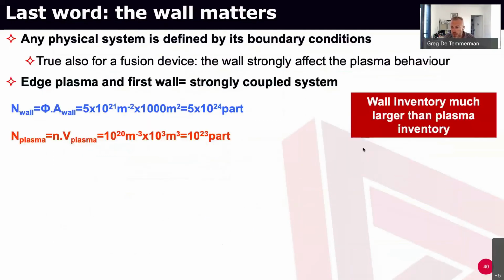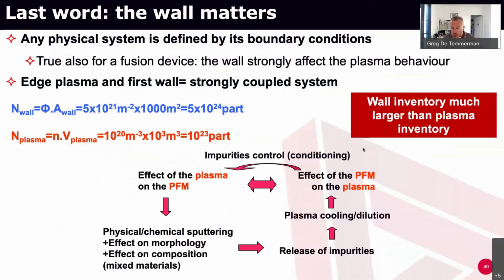And just one last thing, which is perhaps interesting to realize is, as in any physical system, the behavior of the system is defined by its boundaries. And it's also true in a fusion device. Basically, if you look at the amount of particles which are on the surfaces at any time during the plasma, this is much more particles than is inside the plasma. So as soon as you inject the gas, you create your plasma, a lot of particles get absorbed on the wall. And this is typically 10 to 50 times more particles absorbed on the wall than inside the plasma, which means that if suddenly those particles get released, then they change the plasma behavior quite a lot. So this interaction between the plasma and the surface is actually driving most of the performances of the machine, which is quite amazing if you think of it.